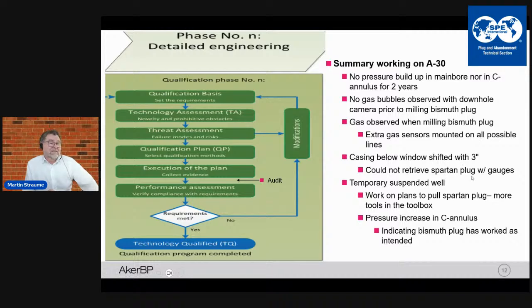And as I said, the casing had shifted 3 inches, and that's why we couldn't get the plug with the gauge out, and that was a pity because the gauge hopefully had worked and we could have actually gone and downloaded the data, but now we couldn't.